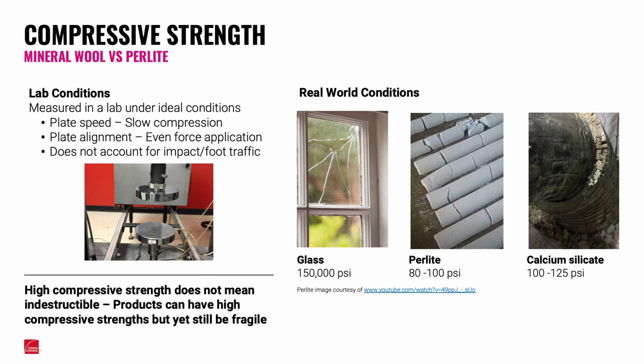So if we look at some real-world examples of what we might encounter, I always think of glass, which has very high compressive strength, 150,000 pounds per square inch of force. But I think we all know that it's not too hard to break glass, damage it. And looking at perlite insulation, that's the center picture here, you can see that we have some cracking there, but that product is rated to 80 to 100 psi. This is cracking that happens during shipment, and so this is not uncommon.